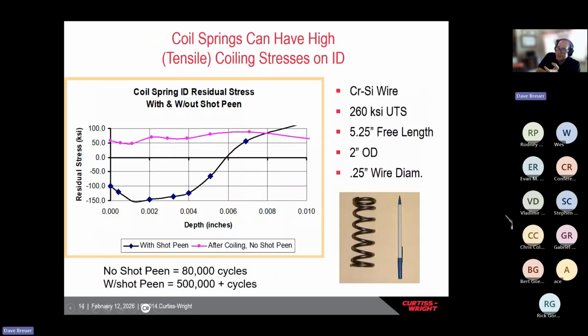Okay, so this happens to be a compression spring. This one here looks at a before and after. If you guys can envision this black curve not existing, what this pink curve shows is the residual tensile stresses as a part of the coiling process. You'll see there's 50 to 70 KSI of residual tension from the coiling. So whatever applied stress the spring has, you have to add this residual tensile stress.